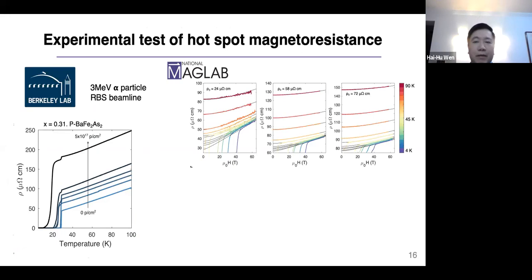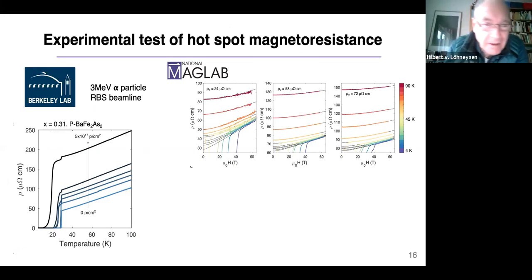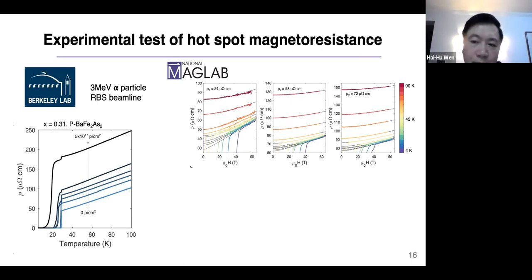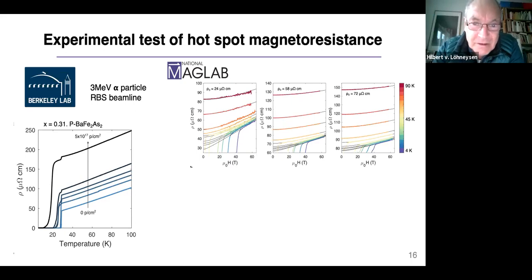Thanks. I would like to comment on that. In this work of Achim Rosch, he showed that if you are at a quantum critical point and have a disordered system, then the hot spot, cold spot interaction will be stronger. When you go away from the quantum critical system, or if you put in more disorder, the system evolves into a different type of universality class. So the resistance, for instance, changes with temperature from T to the 3/2 to more almost linear behavior. I was wondering whether you see any of that in your work.